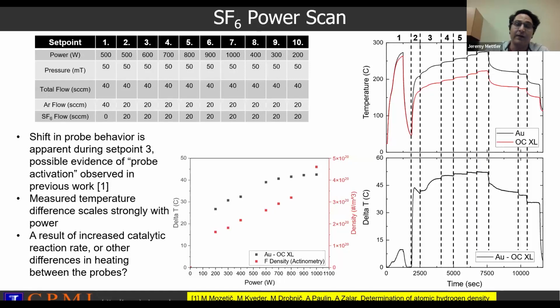And we actually can measure that using the spectroscopy I mentioned earlier. And when we compare the difference between the temperatures of the two probes and the density as measured by actinometry, we get generally the same trend across the power range we've scanned, although you can tell that as we get to higher and higher power, the rate of increase of the temperature difference seems to fall off a little bit there, just as the fluorine density is increasing. So that's a little bit curious, and I'll talk a little bit about why we think we see that later on. But generally, we're seeing a trend that's promising.